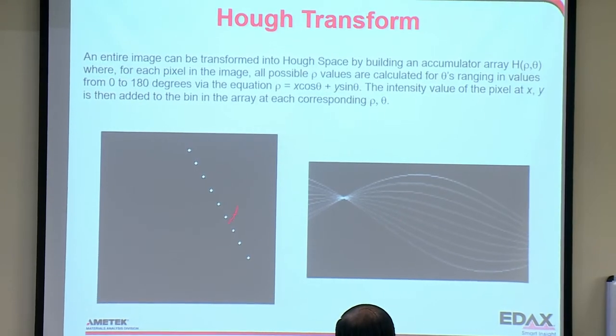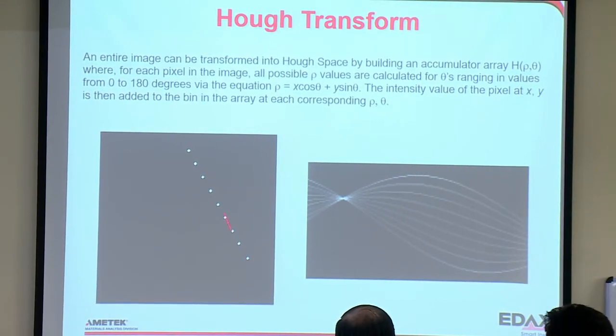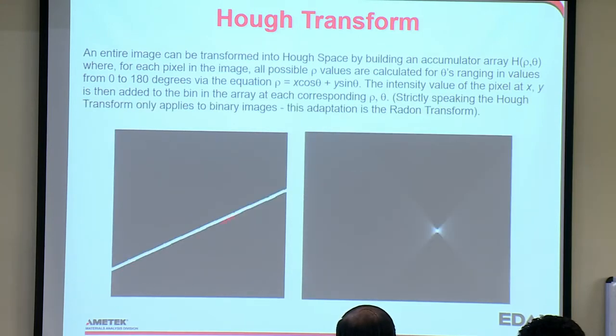So this is actually using our software. I put this image in, and I get this set. You can see the individual curves for each pixel, and you can see the very bright peak where they intersect. Now, if I actually have a line, you can see it forms this characteristic shape. We call this a butterfly, and this becomes important later.